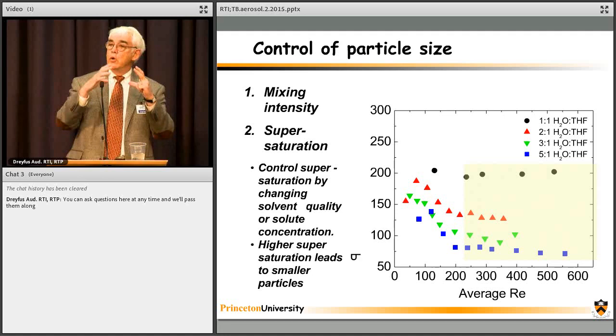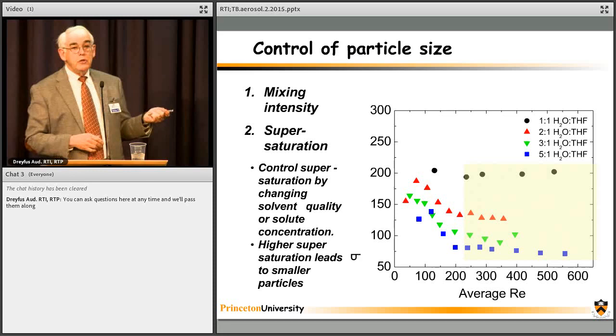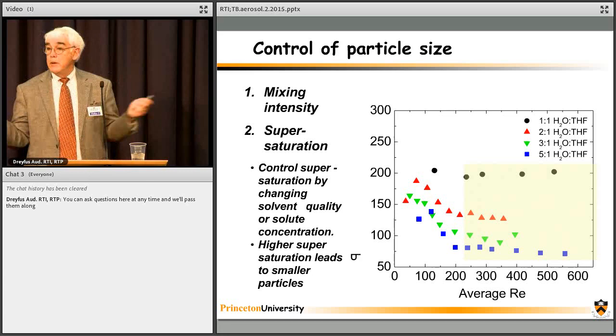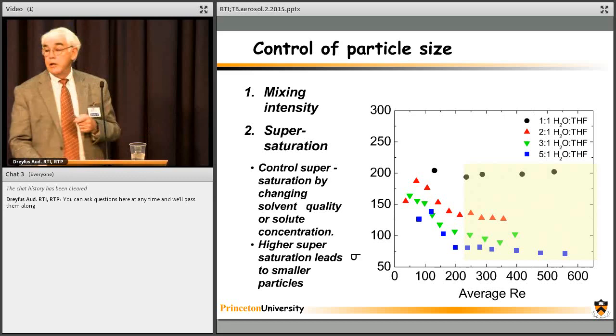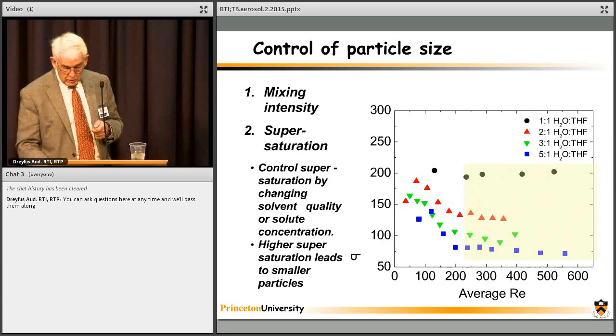If we go to higher supersaturations, that means the nucleation rate goes up because the supersaturation is higher. I have more nuclei, so the beta-carotene accumulates on that greater number of nuclei, so the average size is smaller, and we get down here to about 60 nanometers. So changing supersaturation, which changes nucleation rate, is the main way of controlling particle size.